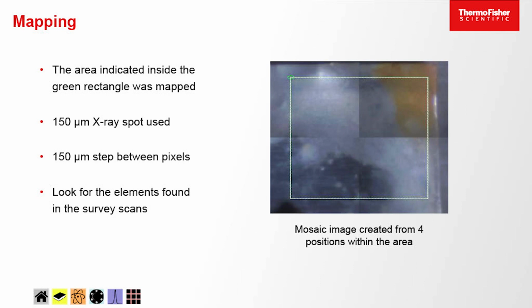And we don't map for everything. So we'll do those survey scans first so we can choose the regions we want to map for, so that we don't spend ages. I mean, you can do a survey scan at every pixel, but it takes a lot longer. It's a lot faster if we can use what we call our snapshot acquisition mode, where we can collect a spectrum in, instead of maybe a couple of minutes, about 2 or 3 seconds, and so we can speed up for something like this, where we're going to have a fairly large array number of points.